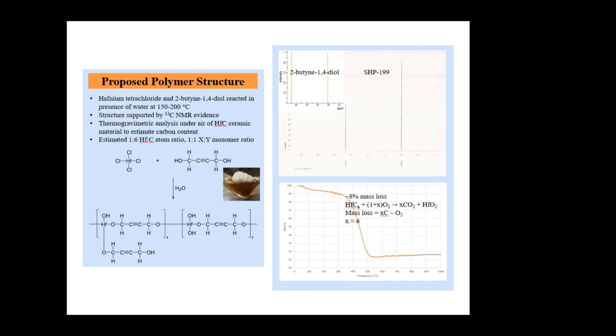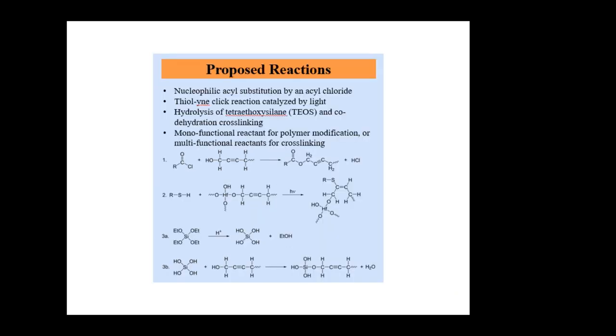We also determined the ratio of X monomers to Y monomers. To do this, we took a piece of pyrolyzed SHP-199 and performed a thermogravimetric analysis under air. Due to the mass loss we observed, we estimate that we have about 6 carbon atoms for every hafnium atom. Since monomer X has 8 carbons and monomer Y has 4 carbons, we can assume that our X to Y ratio is 1:1. With our structure established, we can now consider what chemistry we can perform.